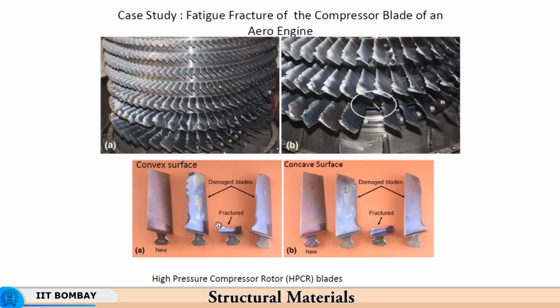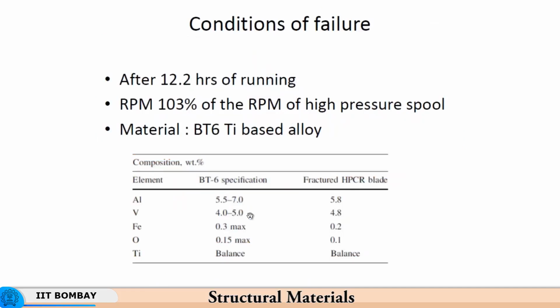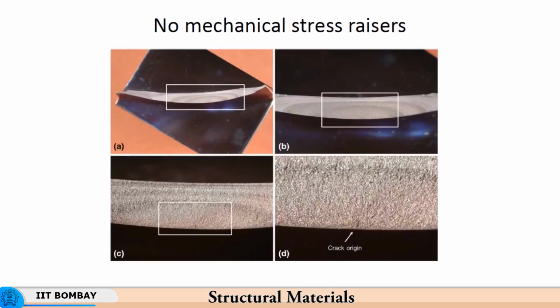However, there is a point at which the blade has fractured as well. So that brings us to a point whether the material composition was faulty, but no, the material composition is not faulty, because all chemical composition parameters lie well within the acceptable limits. So if you look at the specification, the fractured high pressure compressor rotor blade had chemical composition well within the range. So therefore there is no reason to believe that the material was deficient.